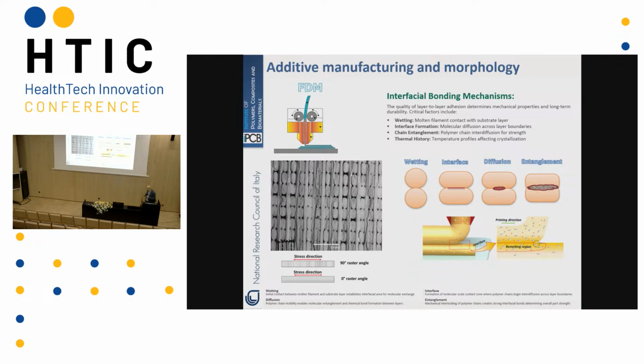You can reduce a lot of the weight of the object, and you can also insert additional features in this object. But the problem that I mentioned before is related to the anisotropy of the material that you obtain when you use this type of technology. Anisotropy is common to every type of additive manufacturing process, but in the case of FDM it is more and more important. Just because imagine you put, one on another, two layers of material that are at different temperature and in different condition, and you have to hope that these two layers stick to have a good adhesion between them.